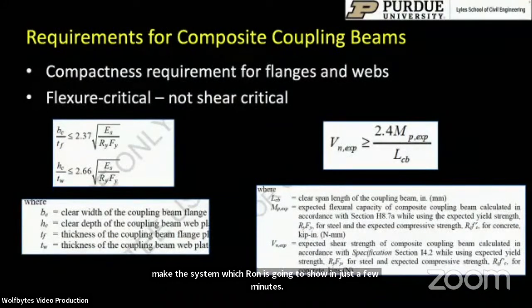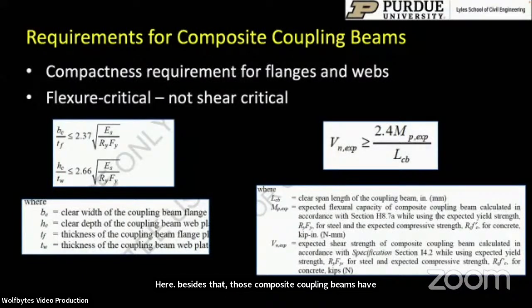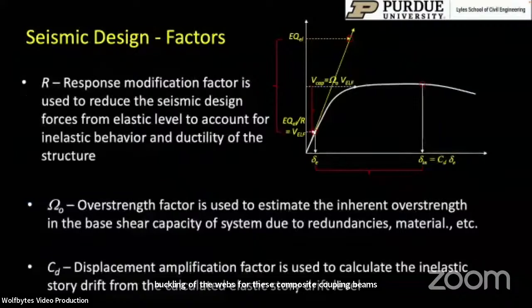Besides that, those composite coupling beams have to meet certain compactness requirements, particularly for the flanges and webs. They are required to be flexure critical. This is a little different from the coupling beam requirements used for reinforced concrete systems. We require these composite coupling beams to be flexure critical, not shear critical, which means that their shear strength has to be greater than their flexural strength multiplied by 2.4 divided by the length of the coupling beams. There are also compactness requirements for the flanges and webs of the coupling beams that take into account local buckling of the flange in compression and web shear buckling of the webs. All of these requirements are now included in the seismic provisions.